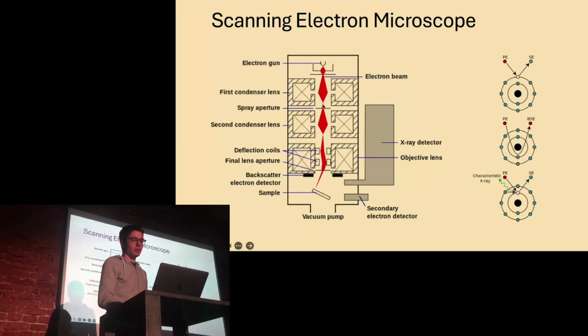Then there is, for example, the aperture. The aperture is setting the current of the beam. So higher current gives you a larger part of the beam and thus a larger signal to noise ratio, but also reduces your resolution. So ultimately, we want to use lower accelerating voltage and lower beam current to get the image with the best possible resolution, but such images are very noisy. If you are wondering what the resolution of SEMs is, it's around 1 nanometer. With the TEMs it is 1 angstrom, like 0.1 nanometer. So with the TEM, we are able to actually see the atomic lattice of the sample. And then there are some scanning coils, and obviously the sample.